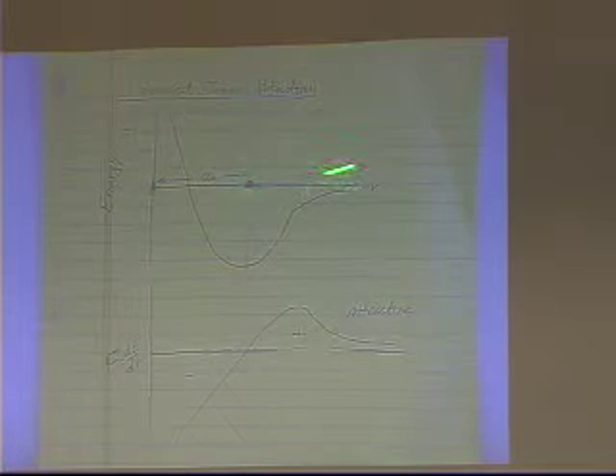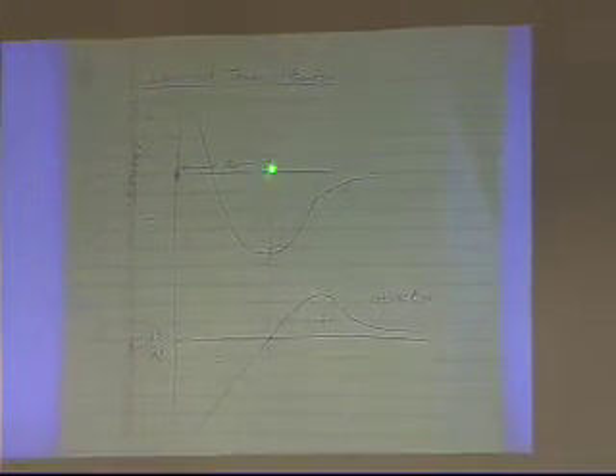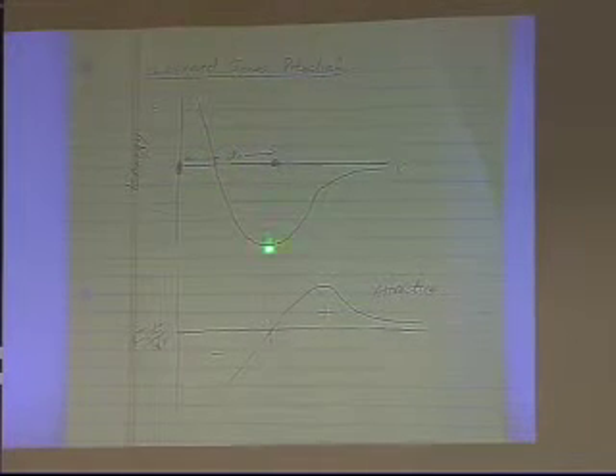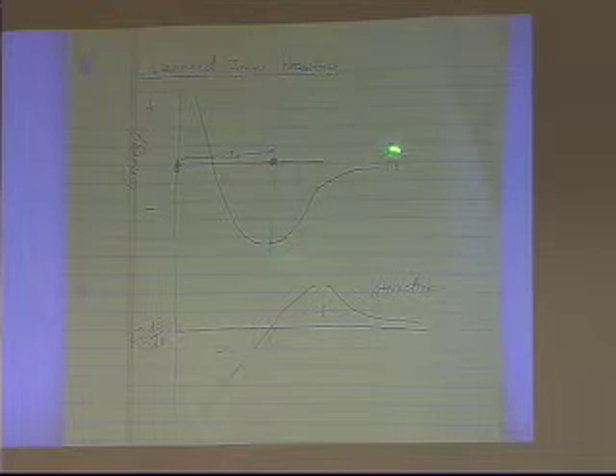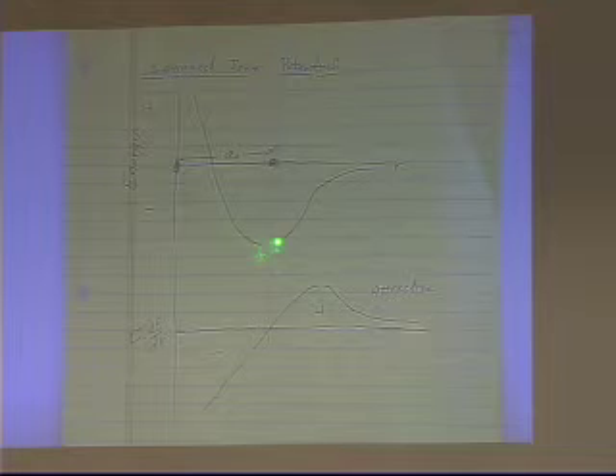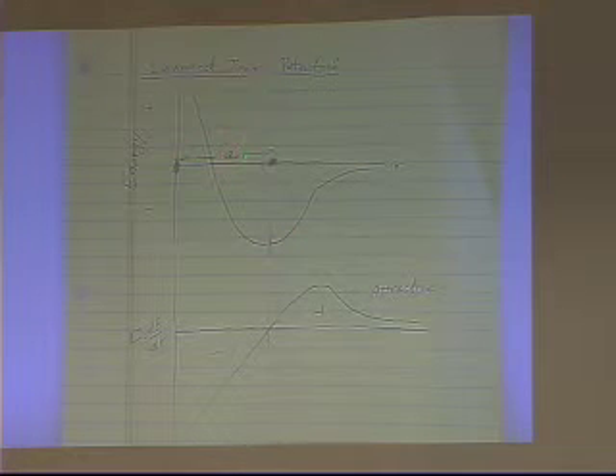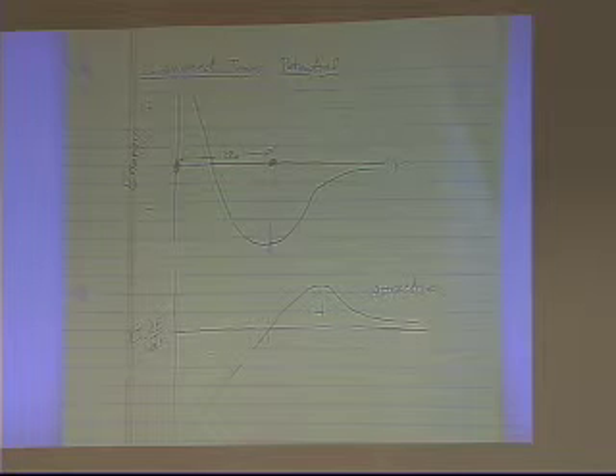Now, if you go back to basic chemistry, in the very first couple of days in a chemistry class, they tell you about something that in the 1920s they called the Lennard-Jones potential, where you plot the energy of two atoms. Here's the atom at rest, and here's another one that you bring in from some distance away. And it comes to some equilibrium distance of separation, and there's an energy of attraction and repulsion in here, okay? It finds its equilibrium spacing at the minimum energy. And that's a0, the lattice spacing in a crystal, the equilibrium interatomic distance. And there's an attractive force, a lowering of energy as you bring them together. And the force of attraction is just the derivative of the energy. F is dE/dr, right?